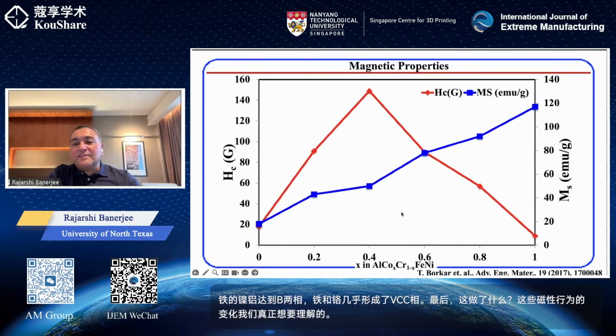Again, the trend in the atom probe is the same. You have a nickel aluminum rich B2 phase with some amount of iron, and the iron and chromium pretty much form the BCC phase. So finally, what do these changes do in terms of the magnetic behavior, which is what we were really trying to understand? If you look at it, it's a very interesting magnetic behavior. Yes, if you look at the blue curve, which is our saturation magnetization, there are no surprises there.